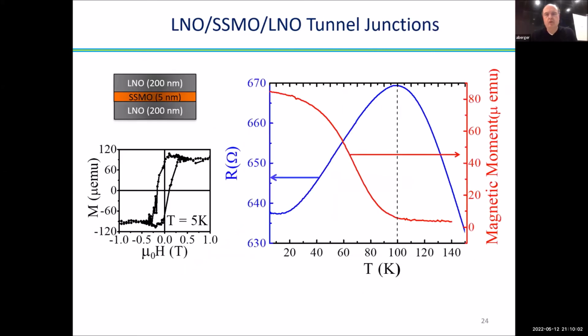Here. Exactly here. So if I were to guess the Curie temperature from the magnetization data, I would come up with a temperature quite a bit smaller than the peak position that you see in the resistance. And even if the TC were the peak position, at that point your effective magnetization is basically zero. So the difference in the tunnel barrier is basically zero. So that's where you should see an initial start of the deviation from the insulating or semiconducting behavior that you see, but you see the peak there. I don't quite understand how this matches with your explanation.